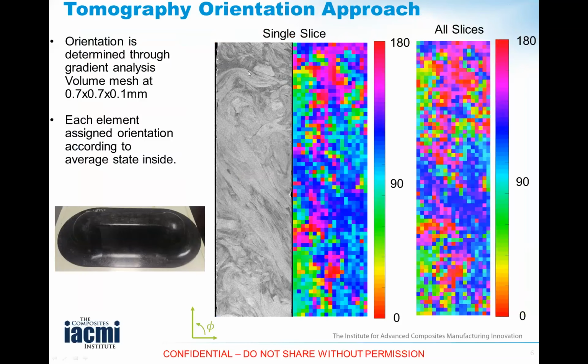So if I look at the intensity of pixels that are represented in the fiber versus in the matrix, they have a large contrast. So if I differentiate the intensity contrast, I will have a large contrast in this direction as opposed to along the fiber. So this is utilized now spatially in 3 dimensions.